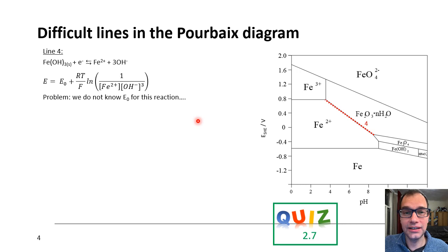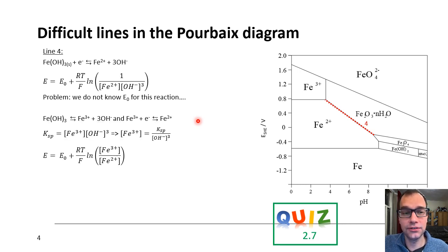Actually, this reaction is a composition reaction, you could say. And if you start thinking about it, it consists of two reactions. First, the iron hydroxide basically dissolves to a very small amount, because we know that will not happen easily at high pH. But it could be a very small amount. And then the next step is that the iron 3 absorbs an electron and becomes iron 2. So we can split this reaction in two, and then we can do some nice stuff.